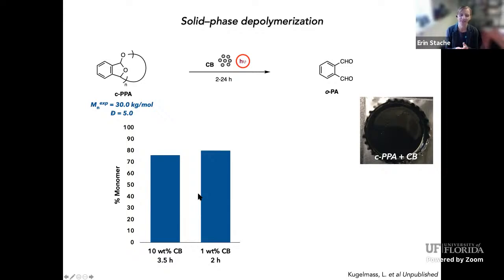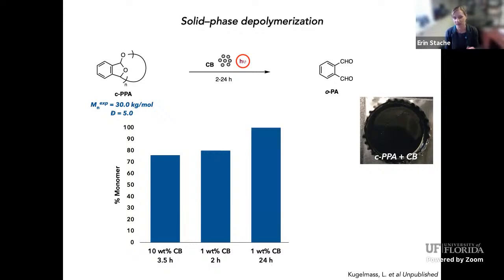And this kind of makes sense. Carbon black absorbs most of the light. It's almost a perfect black body, so it's absorbing all the light. If there's too much in there, it might actually be blocking transmission into the film. And so with 1 weight %, we actually see more efficient depolymerization. And we can push this to about 100% if we let it go for a little bit longer. Sometimes what we see happening is that the carbon black starts to aggregate as the film is depolymerizing, and then that just takes a little bit longer to ultimately depolymerize.